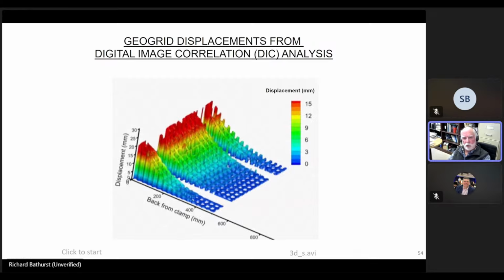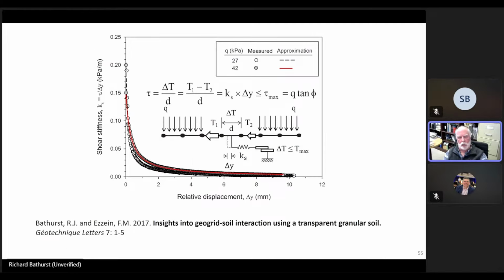So this provides a huge amount of information to develop interface models between the reinforcement and the soil. And from this data, and I don't want to get into large details about the model, the physical data points have been deduced from the DIC technique. And what you see here is the model, which is following very neatly that performance. And so this model provided us with a shear stiffness parameter, which is displacement dependent, that could then be put into our FLAC models to capture this particular geogrid soil interaction mechanism.